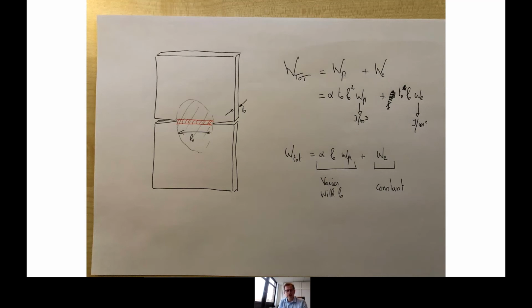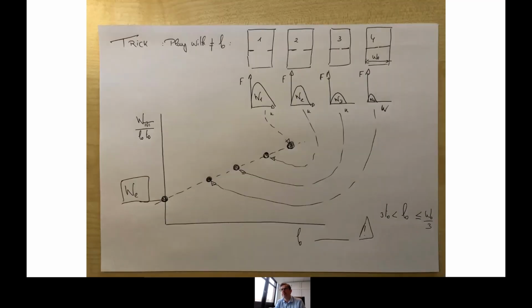There are several rules, and David mentioned some aspects, but Antoine will later give more information about the region of validity and the statistical relevance of the measurement, so I will not talk about that. You understood the idea: you make measurements with different ligament lengths and you measure the total energy. That is very nice because you don't need to monitor crack propagation, which is the difficulty in fracture mechanics and JR curve testing. You don't need to know where the crack is. You just load the specimen till fracture. That also allows working easily on materials at high temperature, for instance, without very sophisticated monitoring of the cracks or sophisticated extensometry.